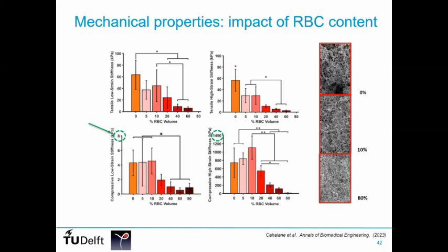We did some SEM imaging of these samples as well. The one here with the 10% red blood cell concentration seemed to be the concentration where the red blood cells that were encapsulated in the network had a slightly different shape. People sometimes refer to that as the octahedral shape, I think, where they seem to be not circular, but having a slightly different shape with some angles.